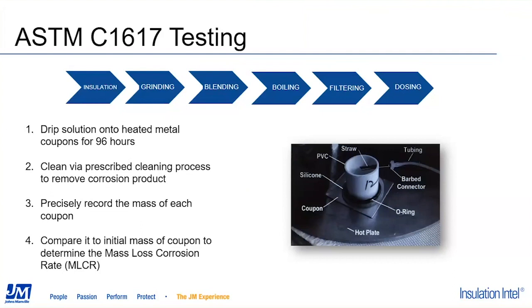That liquid is then dripped onto the surface of the coupon. If you look at the picture on the bottom right-hand corner of this slide, you see the carbon steel coupon sitting on a hot plate with a piece of PVC pipe sitting on top of it, sealed at the joint between the PVC and the carbon steel, and then there is a piece of tubing with a little straw at the end that enters into the PVC pipe. The liquid is dripped onto the surface of the coupon. The hot plate is operating at about 230 degrees Fahrenheit. So as the liquid drops onto the coupon, it boils off, leaving any contaminants or corrosive compounds behind. The dripping and evaporating cycle is repeated for 96 hours.